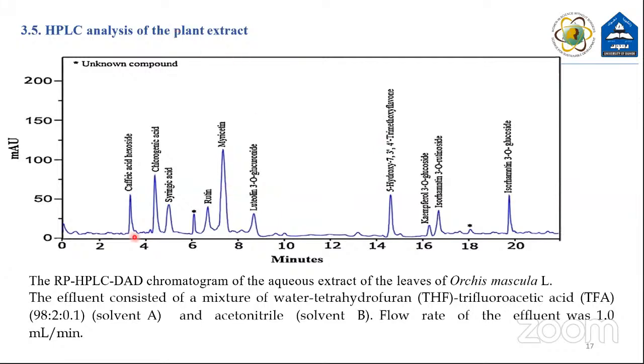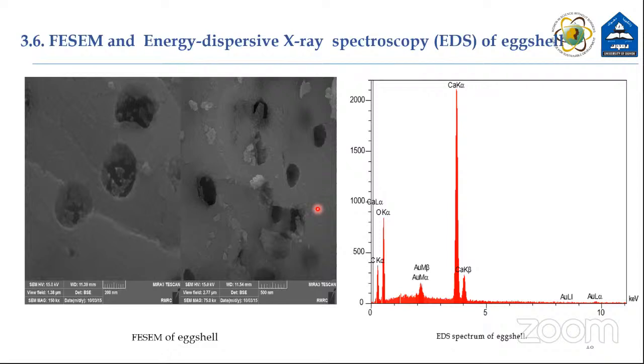HPLC analysis of plant extract: the HPLC chromatogram indicates that our plant is a rich source of phytochemicals and antioxidants, including rutin, myricetin, chlorogenic acid, caffeic acid, and kaempferol, and these phytochemicals or antioxidants can donate electrons to metal ions and reduce them to zero-valent metal. Field emission SEM of eggshell confirmed that eggshell is a macroporous network, which helps to easily form nanocomposites with copper or with magnetite. And we have elemental analysis, EDAX, which revealed that eggshell is composed of carbon, oxygen, and calcium.